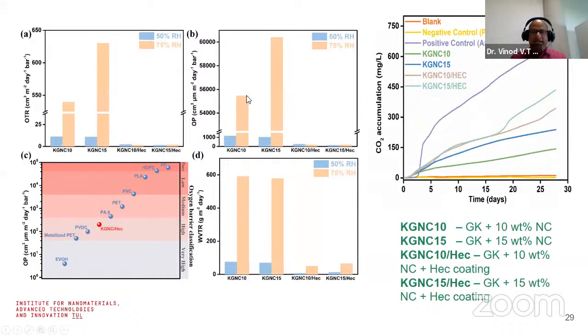So here you can see different compositions of these materials and how the barrier properties at 50% relative humidity and 75% relative humidity look. Under the 75% relative humidity condition, this film shows good properties, and we compared it with other available bioplastics in the market. So our clay-based gum composite film shows a better position among the other materials.